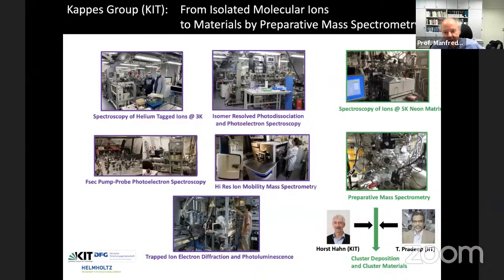We do on these ions also isomer resolved photoelectron and photodissociation spectroscopy. So sometimes the systems in gas phase have multiple frozen out conformers, so it becomes interesting to resolve them from each other because they have different spectroscopic properties. We're interested in time-resolved spectroscopy of the ions. We study that with femtosecond time-resolved photoelectron spectroscopy. And we have trapped ion experiments where we look at the photoluminescence of the species in gas phase without any matrix. And we also study their structures by electron diffraction if the structure is not already known from condensed phase.